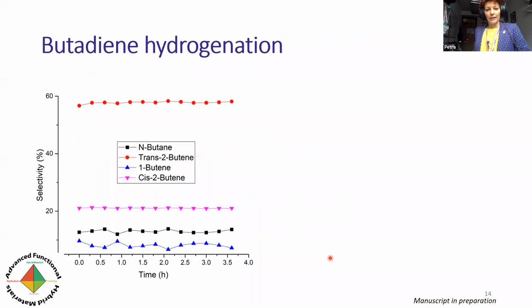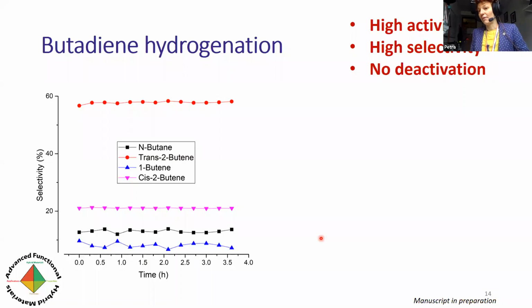of butadiene to butane. And indeed, when we exposed our catalyst to the reaction mixture, we found that it was fairly selective for the formation of trans-butene. And more importantly, we didn't have a lot of butane formation. And you will see in a moment, I'll give some results from the literature in which a much higher concentration of butane is formed. So for us, it's just about 10%, which is still considered fairly selective. We also found that it was very highly active. And what's important is that this was probed for 4 hours, but there was absolutely no indication of deactivation. Previous results showed that in a matter of half an hour, the catalyst already started to deactivate. So we did not notice anything like that.